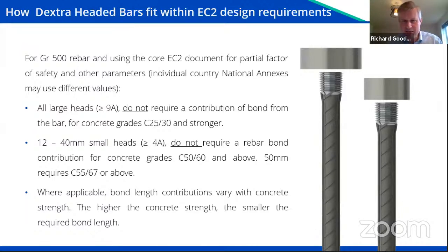So how do our heads then fit in with these requirements? Well, if you take a grade 500 rebar and the core parameters within Eurocode 2, so parameters of partial factors of safety and the other factors, if you use one of our large heads, that's a 9A head, you won't need a bond length contribution provided the concrete is C25/30 or stronger. And in Europe, this is how we designate it. So the C25 is the cylinder strength, and 30 refers to the cube strength.